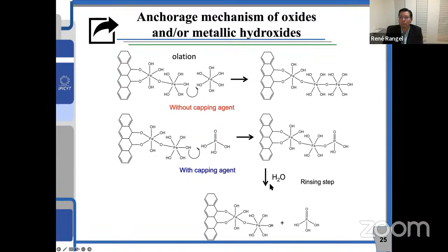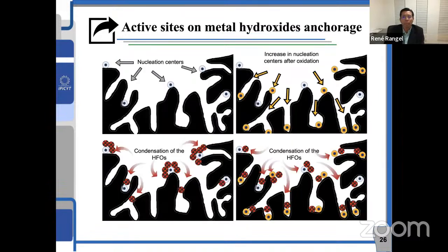And then with a simple rinse with water, we get rid of the capping agent, and we end with very small particles. And that's very important for the application. In that case, the arsenic will remain on the material, and the metal oxide will not leach to the treated water. That's very important. Well, in this case, of course, as you saw in the last slide, the metal oxide will anchor on the oxygen-containing groups of the carbon material.